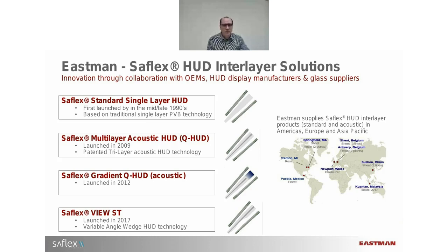As cars became more silent, more comfort was needed, Eastman introduced around 2009 a similar interlayer, but with acoustic performance. So you see in the middle, there is an acoustic layer, which brings a nicer sound level into the car. Next generation was adding a gradient band in blue, gray, or green, depending on the customer needs. But if we look at these three interlayers, they are mainly adapted to the nominal driver. So it means that average people didn't see a double image because the PVB was fine-tuned in thickness for that average person. But if you were unlucky and you were a little bit taller or a little bit shorter, you could be suffering from a double image, or ghosting, as we call it.